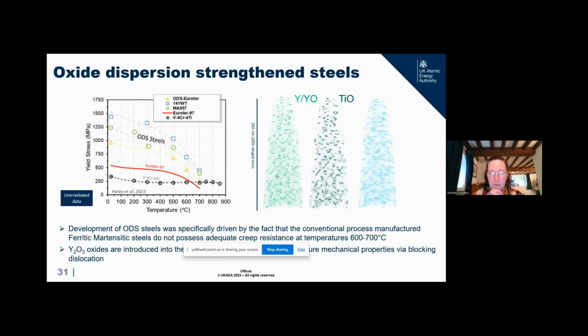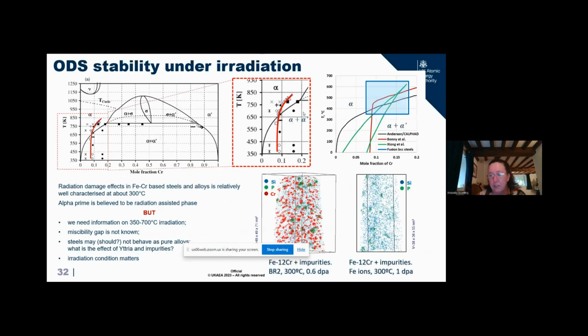I mentioned the oxide dispersion strengthened steels because these really show a lot of promise if we can get them to work. The data on the left-hand side here is unirradiated data, but you can see how much better in a stressed environment at the temperatures we're interested in, the ODS performs relative to the RAFM if we can preserve that relationship post-irradiation. So we're using yttria as the primary oxide dispersant, and we've exposed some of those samples to irradiation. And one of the things we know is that if we use a self-ion irradiation, we do not see the generation of an alpha prime phase, which means the segregation of chrome in these chrome-based steels.